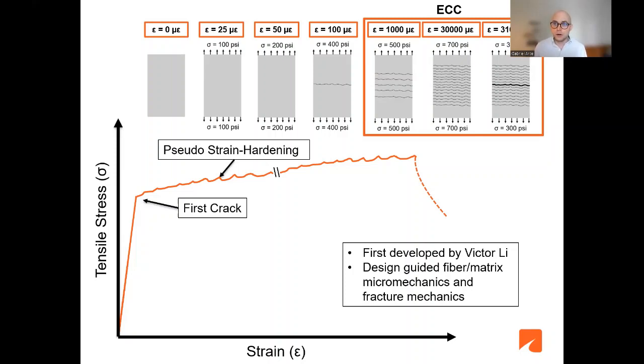Now, how does this mechanism occur? How did this ECC come to life? This ECC was first developed by Professor Victor Li. In fact, in the early 90s, the development of this material started, and there has been a lot of development in the past few decades to enhance their properties and make them more practical and more cost-effective. How do you design these materials? These are designed based on fiber-matrix micromechanics principles and fracture mechanics principles. In a nutshell, the insight that these principles give you is that you need to use fibers with high tensile strength. And also, you need to control the bond between the fiber and the cementitious matrix.